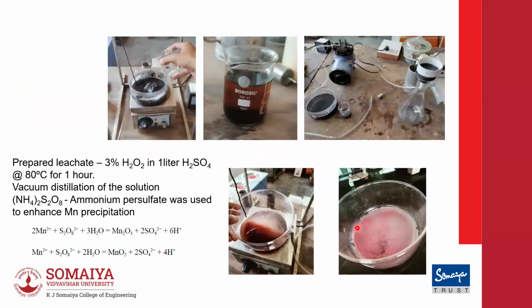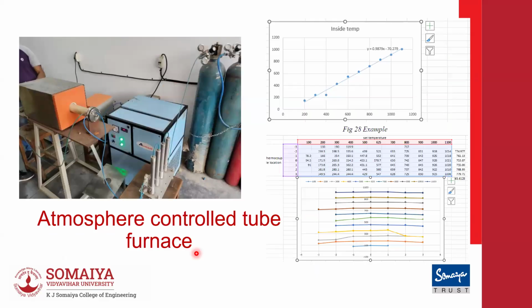The black mass was then mixed with hydrogen peroxide in 1 liter of sulfuric acid and heated at 80 degrees for an hour. And then we did vacuum distillation, through which we got this sort of pinkish salt. So this is the expected reaction that we're looking at. We are expecting that pinkish salt to be manganese dioxide. In parallel, we also tried to do pyrometallurgy for another batch. This is the tube furnace, which can be heated under inert conditions and can go up to 1200 degrees Celsius.